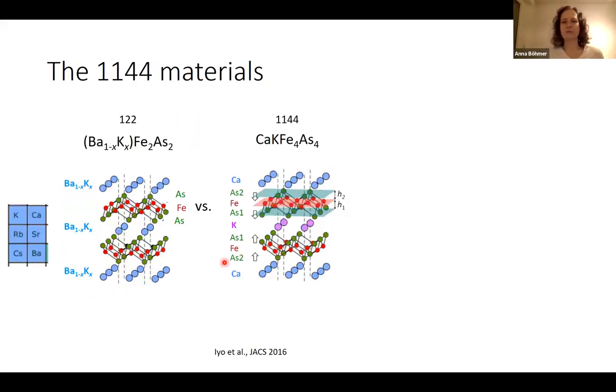But let's look at the 1144 materials and how they are special. This comes up in contrast to the hole-doped 122s. When we have a 122, we start with an alkali ion on the A site, and to hole-dope it, we alloy with an alkaline earth, and to hole-dope it, we alloy with an alkali element. Oops, tongue twister. So there is a mix of these two elements on the A site.